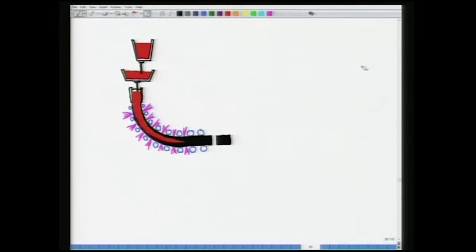Now, this entire process is attained by combining ladle, tun dish, mold, water spray below the mold in such a way so that the speed of withdrawal of the partially solidified product from the mold is adjusted to the speed of pouring of liquid steel from ladle to tun dish and tun dish to mold. So, the figure shows the arrangement of different vessels in a continuous casting.